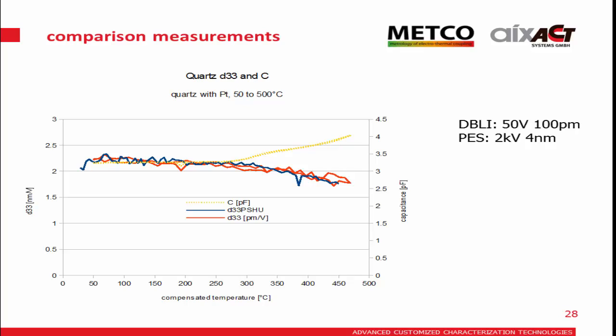And we did some comparison measurements. I think Paul will show more details on that, but that was just the quartz, and we could see on the DBLI we have much lower amplitudes, but we could see a similar behavior across temperature. And on the PES system we apply 2 kilovolts, which gives us about 4 nanometers, which is really close to the resolution limit of the laser, and we already have to correct for crosstalk and other influences, but at least the shape nicely fits. And the further work is to correlate this also with the impedance measurements on the NPL system.